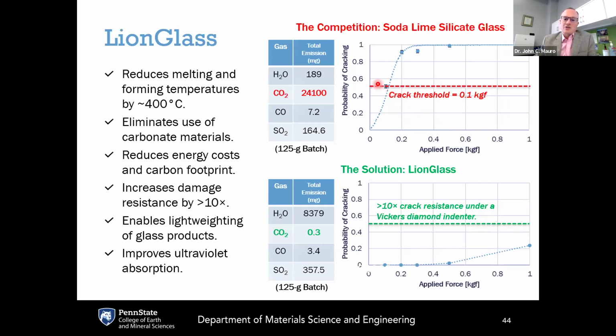The crack initiation threshold occurs at this 50% crossover, which for soda-lime is about 0.1 kilograms force. So here you've got a 50% probability that the glass is going to crack. And then if you go above that, it quickly becomes 100%. With LionGlass at 0.1 kilograms force, that's got a 0% probability of cracking.